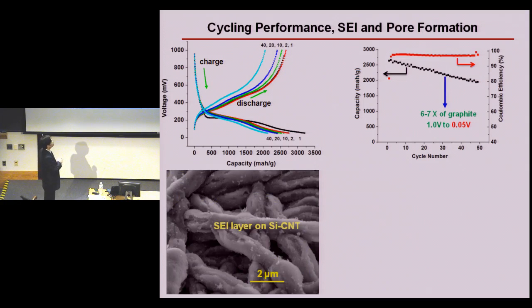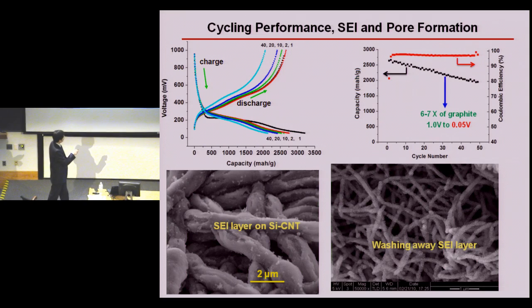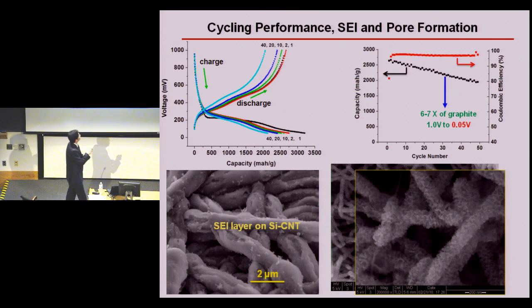So we believe this is due to the electrolyte decomposition at the interface. As you are charging the battery for the first cycle, you decompose the electrolyte onto this silicon carbon nanotube surface. This is the reason why we see a fluffy layer on this silicon nanotube surface. And after we wash away this layer, we see the silicon carbon nanotube structure become highly porous. This may explain why there is a constant decay of the capacity, because as I said, during this process, silicon will tend to break, and that will decrease the capacity because some silicon is detached from this silicon carbon nanotube core-shell structure.